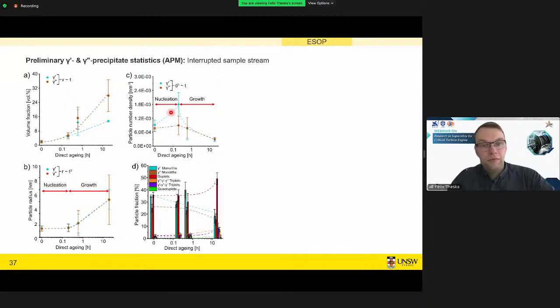We also see that we start with predominantly monolithic and duplet particles, which then, well, the duplets increase in fraction, and then the monoliths transform into the triplets.